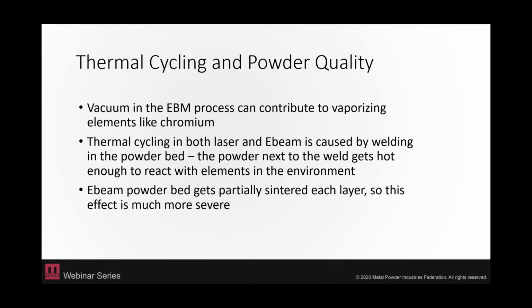So these materials do get deposited on the chamber walls, and that can be a source of contamination as well if you change your powder out. So on our electron beam systems, whenever we are changing a feedstock, we actually take any piece of hardware out that we can, and it gets bead blasted to remove that layer of metallization. And then we actually grind down the chamber walls to remove that layer as well. So anything that can't get removed, it gets ground down.